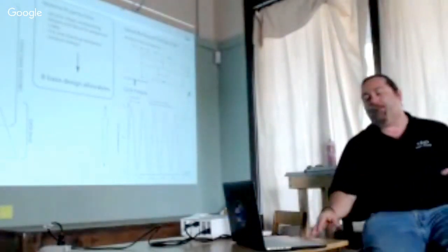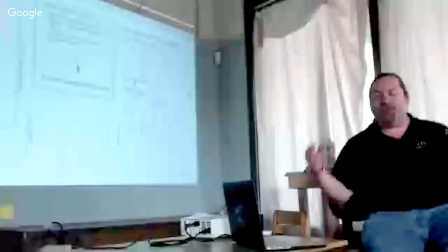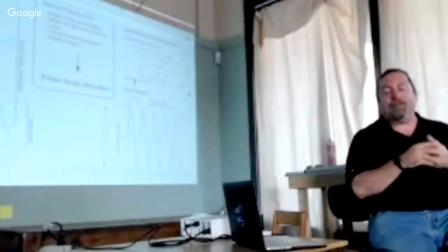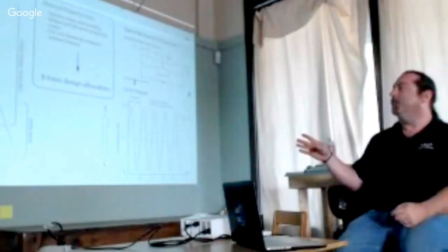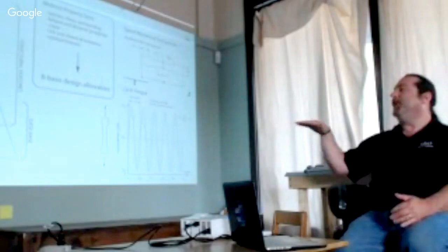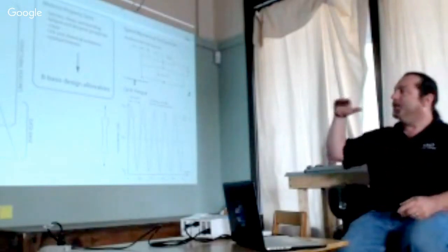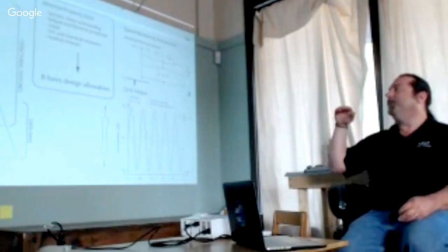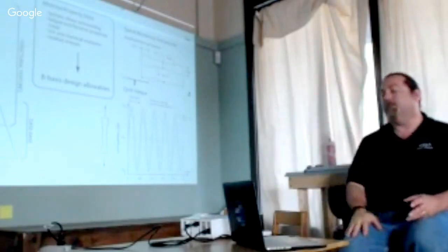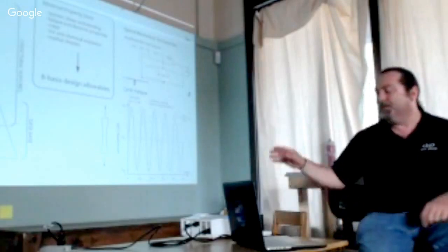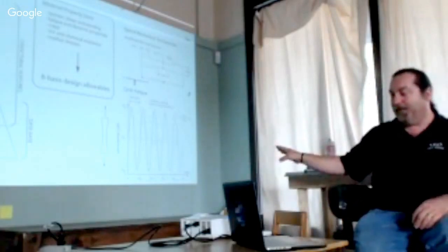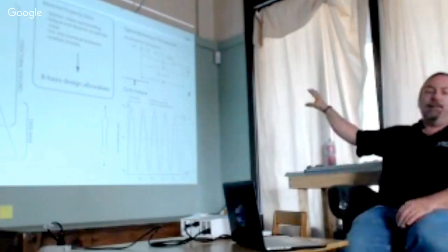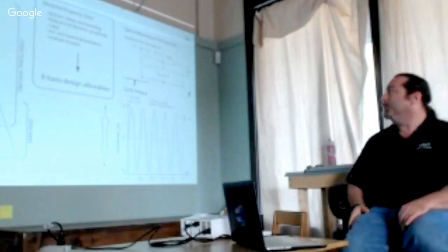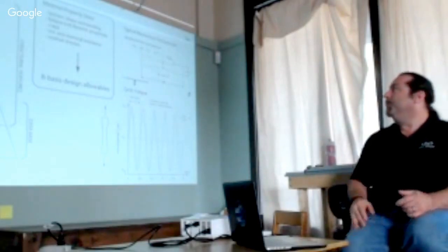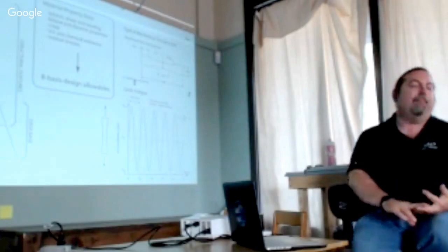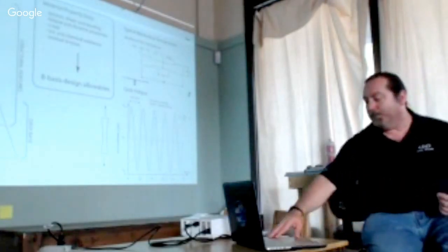Just looking at mechanical properties. When you design a structure, this is typically based on the Composite Materials Handbook approach, where you do coupon level testing to get your basic material properties, and then you move up in complexity through elements and details and subcomponents, and then full vehicle structural testing. It's also showing the fatigue testing that we do, and the standard flat dog bone coupon that we use for tension testing.